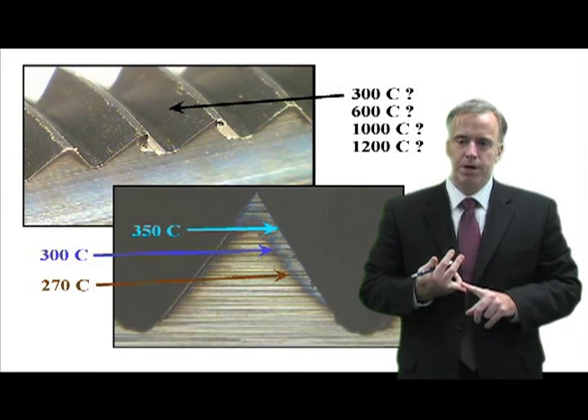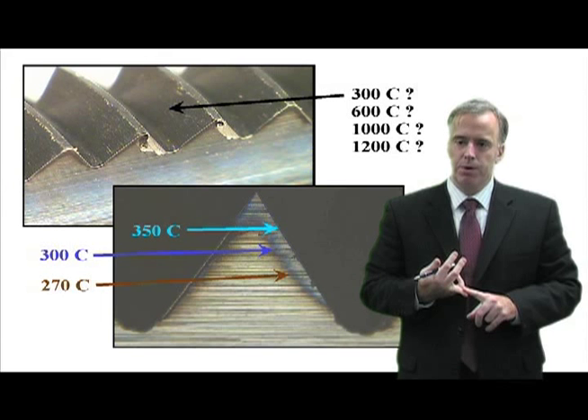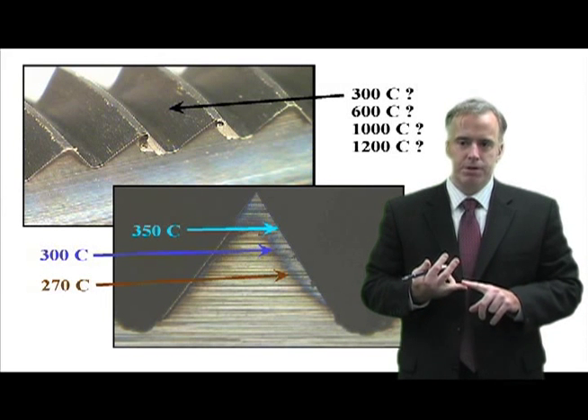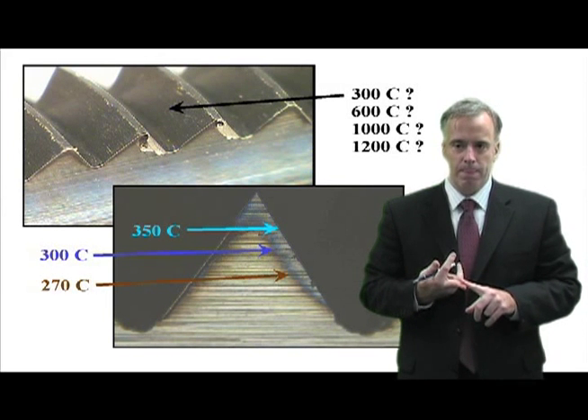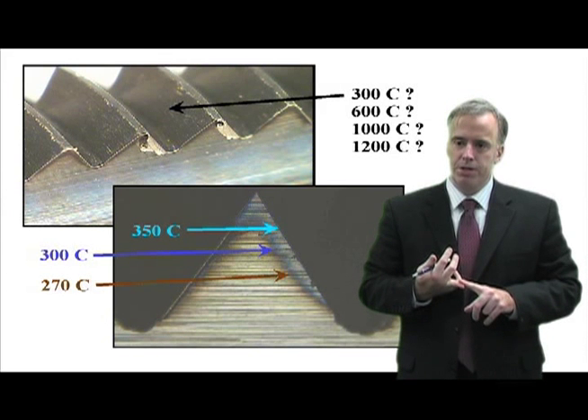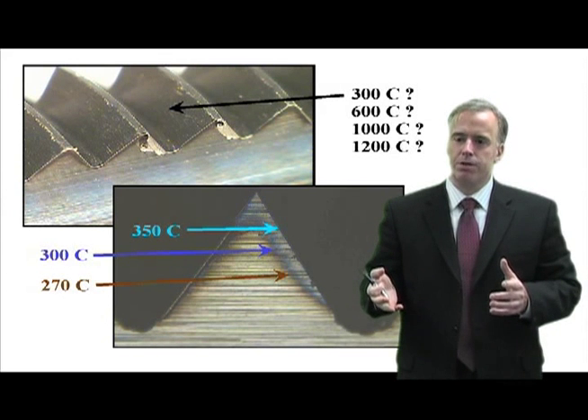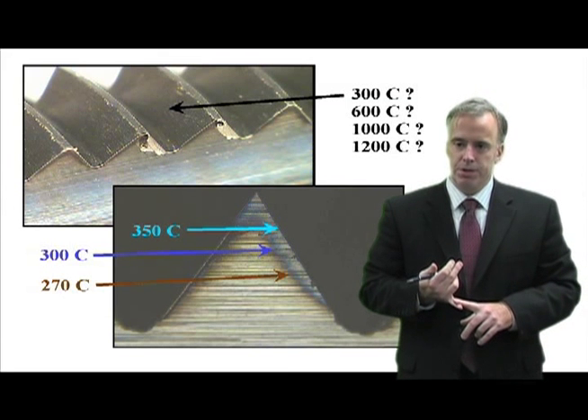I've seen many grinding operations with no oxidation burn whatsoever, but when we tested for genuine thermal damage, they were burned to hell. I've seen operations with brown, yellow, and blue marks that tested just fine for genuine thermal damage.